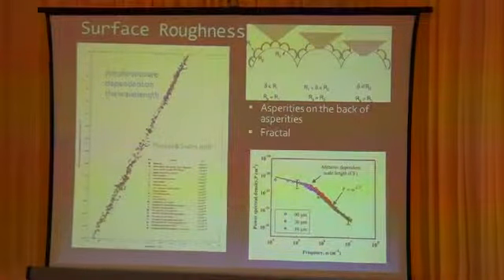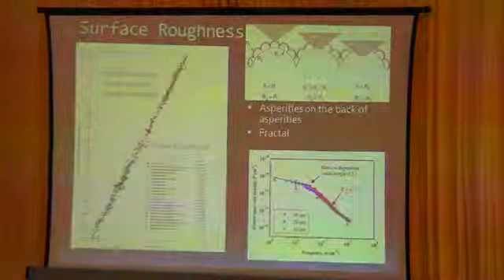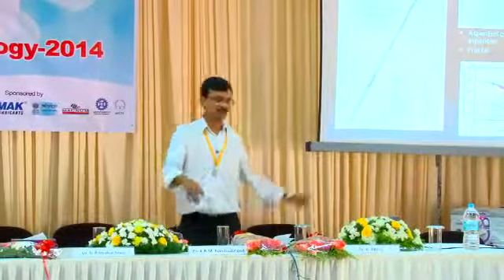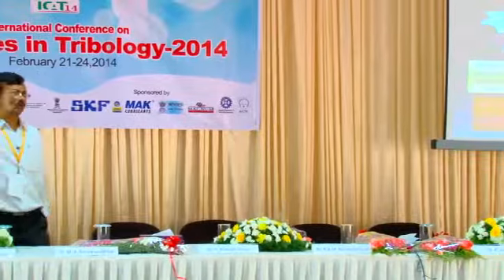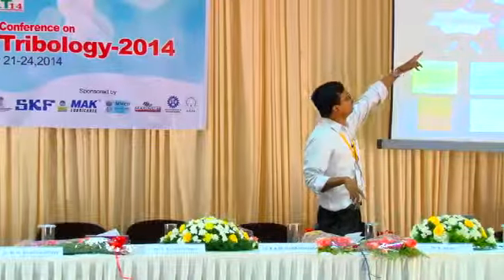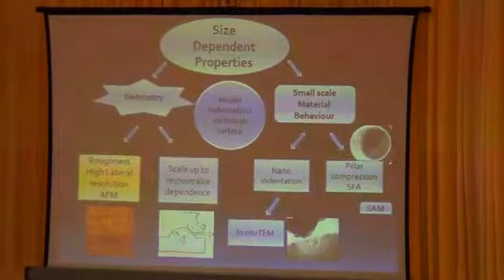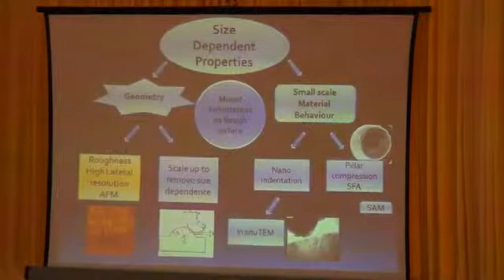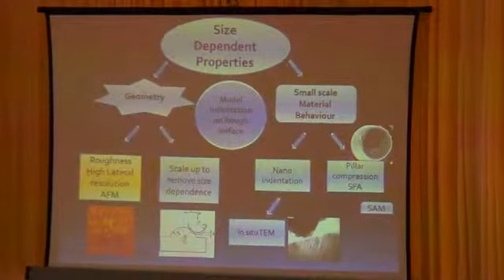So by combining electrochemical polishing and mechanical polishing, we have shown that we can generate very, very flat power spectra of the surface. Okay. So that is why we are interested in doing these size dependent properties. Size dependent properties depend on both small scale material behavior as well as geometry.